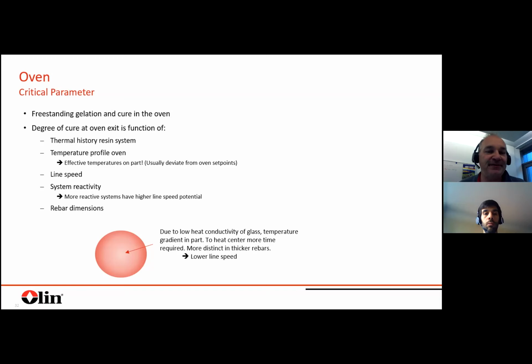Here it has to be considered that the temperature settings of a post-curing oven are not the temperatures which are effective on the part, but I think everybody who was operating this kind of equipment is aware of this. But I think it's quite important to understand what the real temperatures on the part are and how they correlate to the set points. The line speed, so this defines the time in the oven. As mentioned, system reactivity. Higher reactive systems for sure have higher line speed potential. And critical for sure is also the dimension, especially in the rebar, if you go to thick ones with glass.